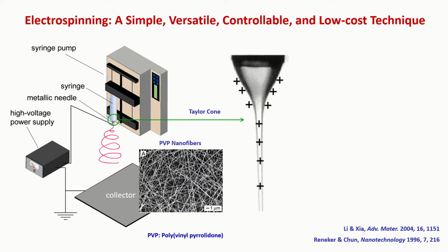And this jet will be basically continuously ejected from this liquid droplet, and its size becomes smaller because of this stretching force coming from this electrostatic repulsion, and eventually the solvent will evaporate quickly, and the polymer will precipitate out as fibers. So it's a very simple idea. It can be applied to many different types of polymers to generate these very thin fibers. Could be from 20 nanometers all the way to several micrometers.